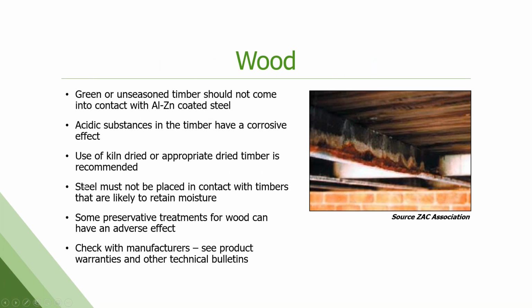Wood: green or unseasoned timber shouldn't be in contact because of the moisture. Sometimes there are acidic substances in timber as well that can be corrosive. So you want to use kiln dried or appropriately dried timber. Anything that's going to hold moisture is going to be problematic. And if it's treated with fire retardant, a lot of fire retardants are copper containing, and that copper is going to leach out and you're going to get galvanic corrosion with the Galvalume panel.